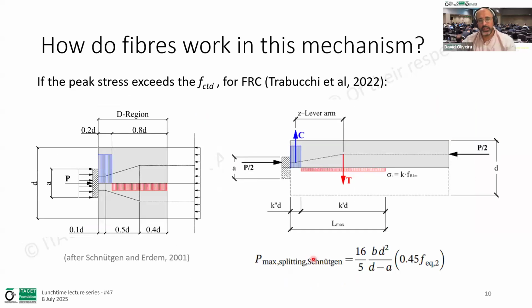So a few people looked at how we can do this for fiber reinforced concrete. And here I present some of the work done by one of the groups from Italy, Trabucchi, in 2022, but he was discussing an earlier model from Schnütgen and Erdem from 2001. So this is as early as I'm aware. There might be others, but Schnütgen and Erdem still adopted some linear elastic concepts and limited the distribution of stresses under highly concentrated forces on the joints, limited to a disturbed region or discontinuity region, as we call it here, that is similar to those estimated by linear elastic solution. The only difference is that they suggested that we could use the residual flexural strength here, converted to an equivalent axial tensile resistance.